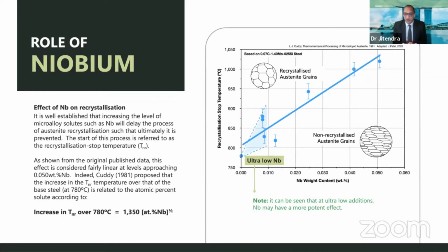But what I would like us to think about and look at for this presentation is the very bottom left of the graph, where you can see this blue shaded area, which is called ultra-low niobium. So this is an area which is typically not associated with niobium. And what we've been finding, looking at this graph in a lot more detail and researching this over the last 8 years, is that at these very low levels of niobium, there is significant potency and significant benefit which can be seen, which we've not really typically looked at, because traditionally we've associated niobium at much higher levels and also rolling at very low temperatures as well.